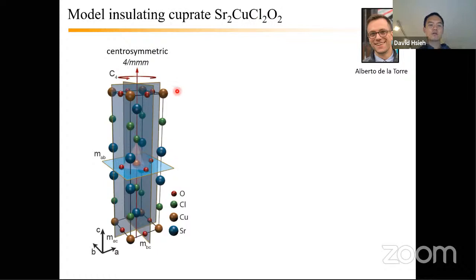They're centrosymmetric. They adopt this tetragonal 4/mmm point group structure. Okay, so here again, 4 refers to C4 symmetry about the c-axis. And the m's are basically three orthogonal mirror planes, m_ab, m_ac, and m_bc. These are the three different shaded slices that I've shown.